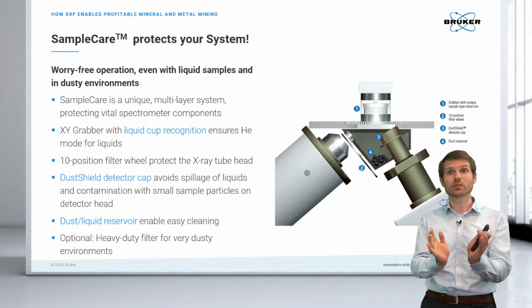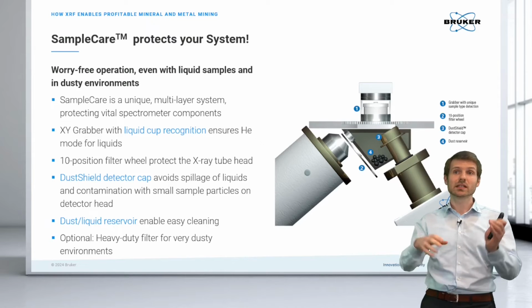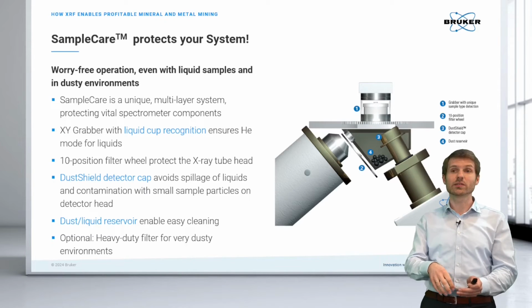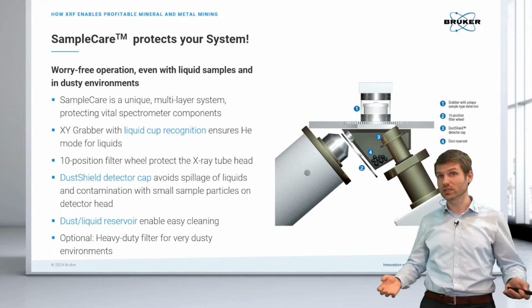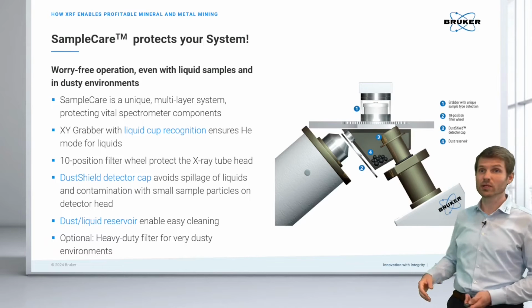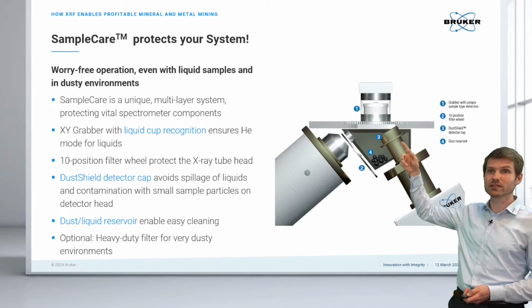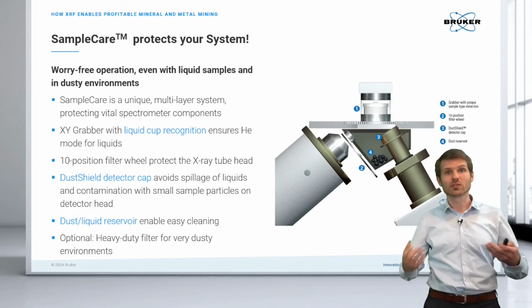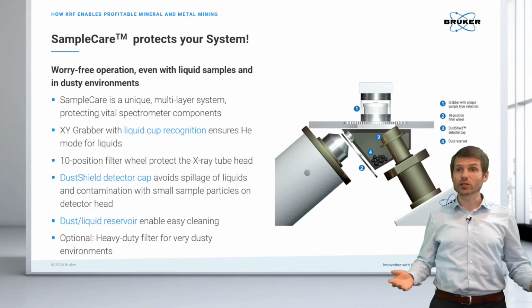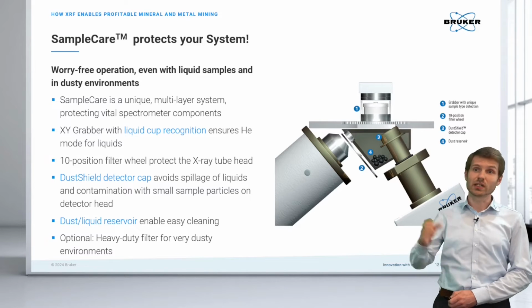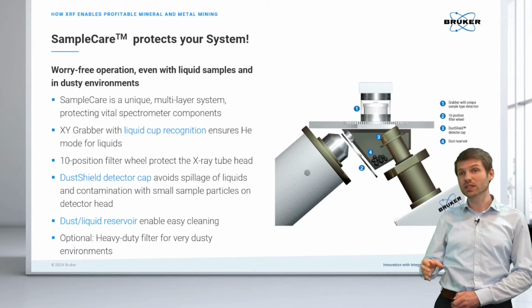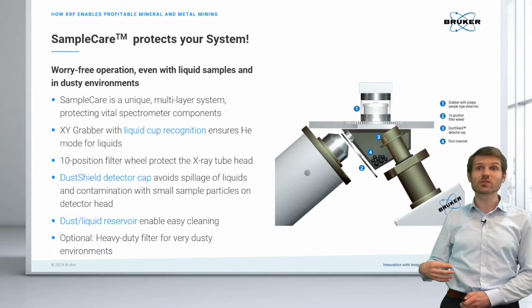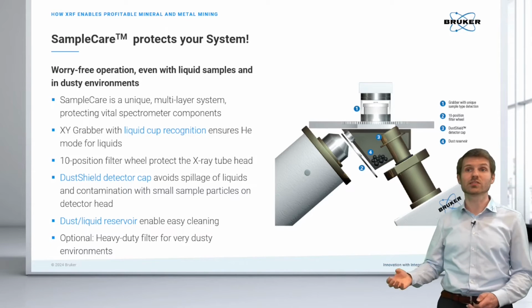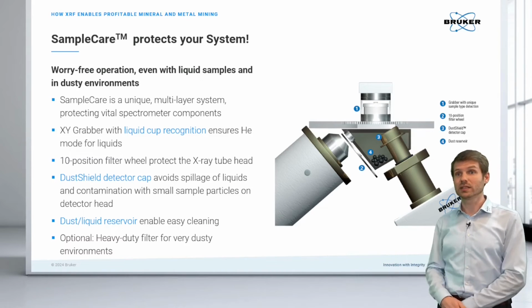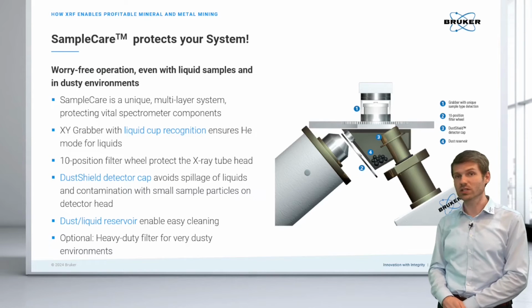Then we have a reservoir. So in case a sample breaks, it goes into that reservoir and you can clean it. So you don't need a service technician to come. And we have a detector cap that protects the detector from these spillages. And also with the XY auto changer and our smart UPS, which can be hooked up to the system, the samples will be retrieved from the sample changer in the case of power outage. Another point that can be important for remote locations.